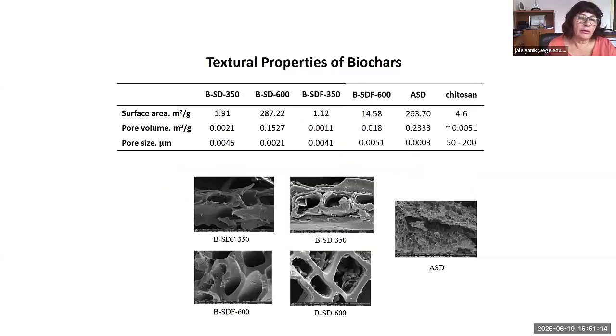On this slide, you see some textural properties of biochars. Also, for comparison purposes, the textural properties of chitosan. Chitosan is commercial and generally used as a carrier. You see most of the biochars have higher surface area and higher pore volume than the commercial chitosan. And it is also interesting that the pore size of chitosan is much higher than our carriers.